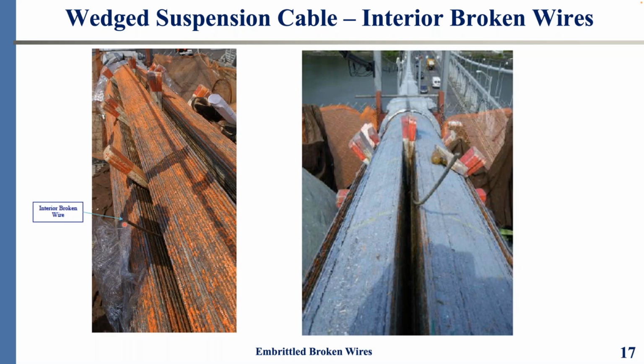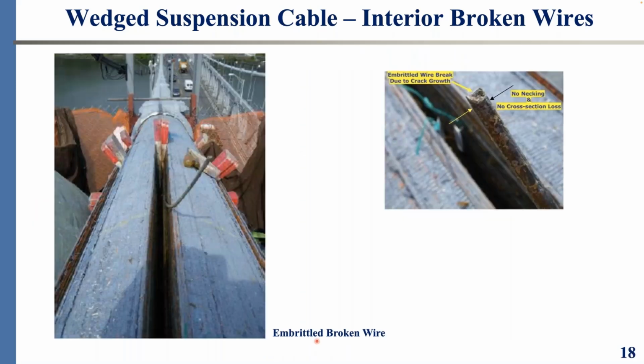One thing to say from the get-go, that all these broken wires are embrittled. If we zoom in on the end of the broken wire here, you see that the wire is full cross-section. This wire is about 80 years old when this picture was taken. It has the full cross-section, full diameter, no necking, but embrittlement is vivid and clear.